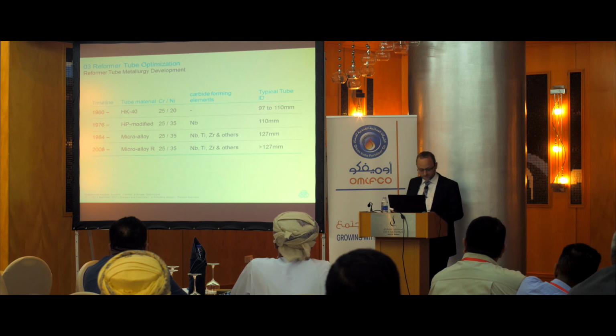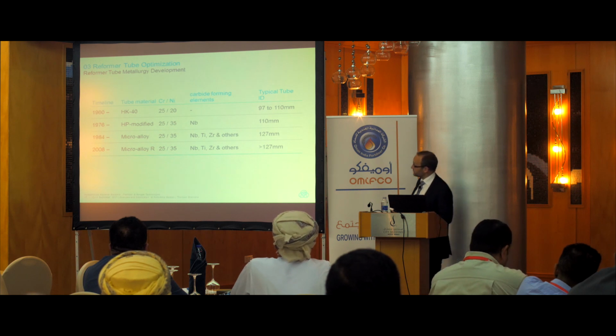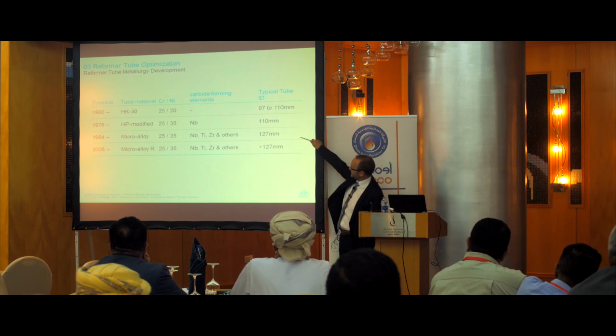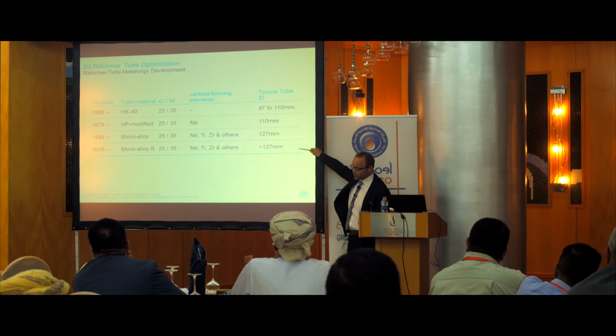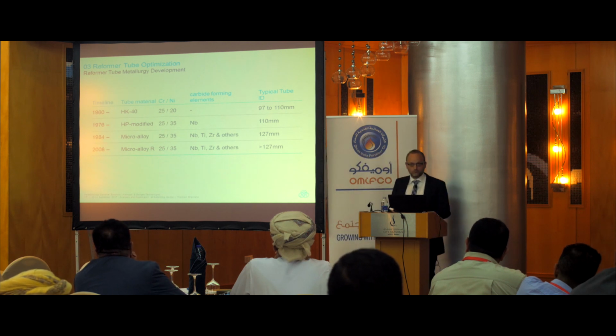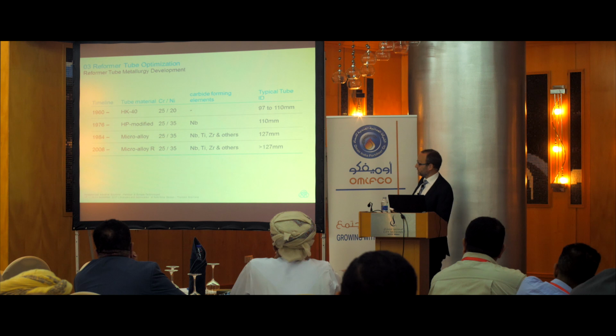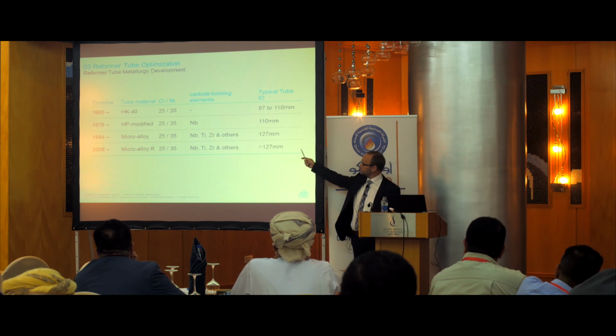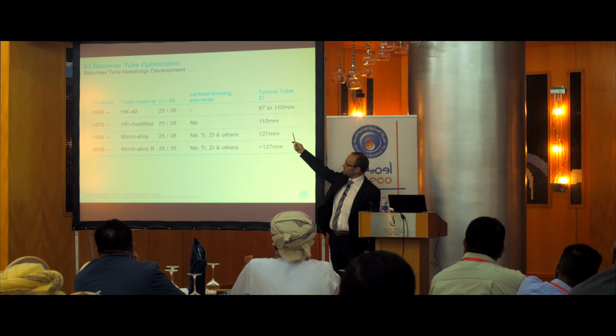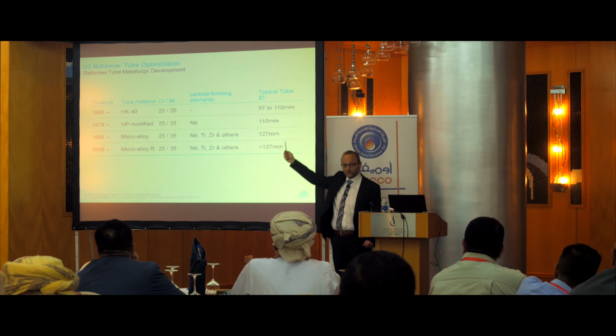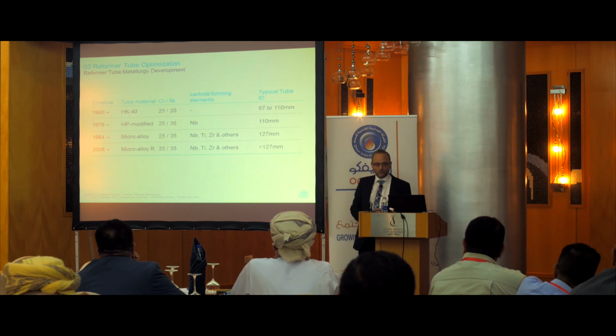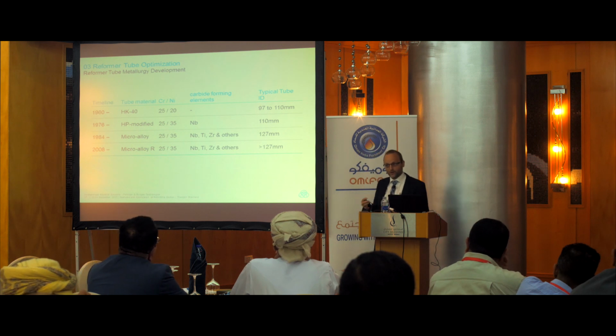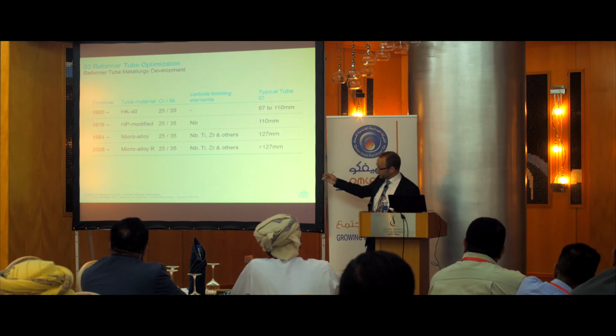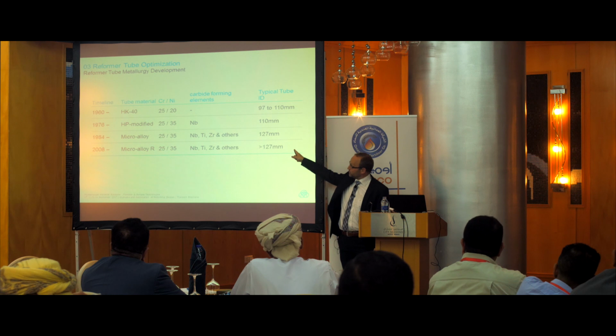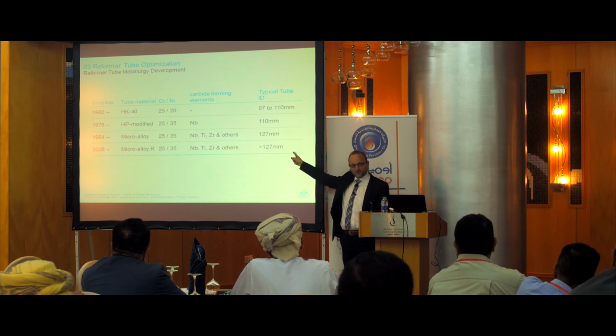The difference between the standard microalloy, which has been available since the 80s or beginning of the 90s, and the new one is, first of all, that the new one is optimized for reformer operation, while the first one was also available for ethylene crackers. Ethylene crackers have a much higher operating temperature. So for this one, tube manufacturers could, for example, reduce the silicon content.